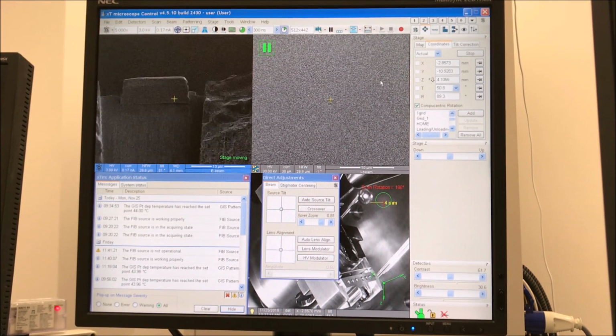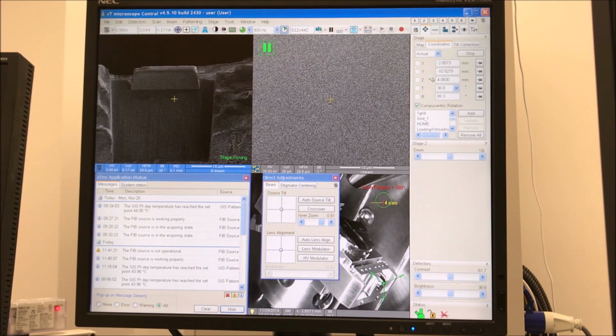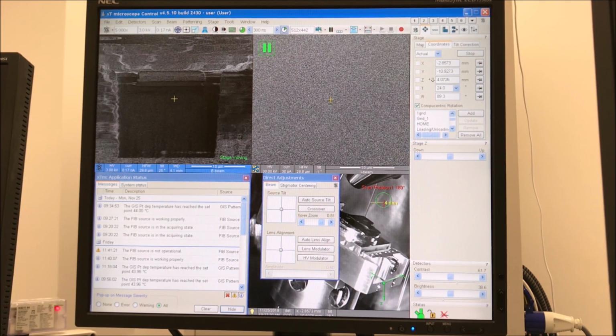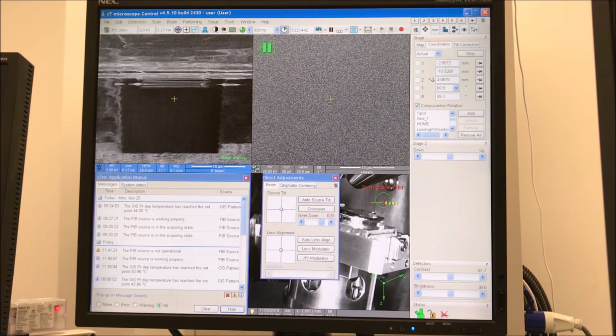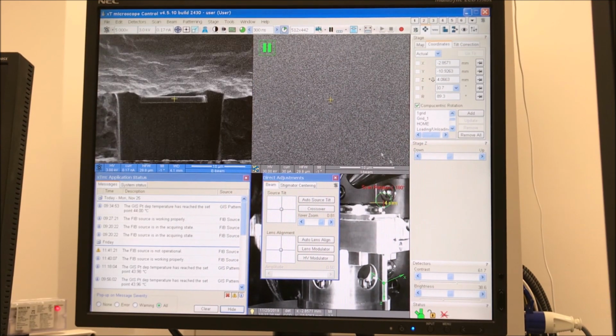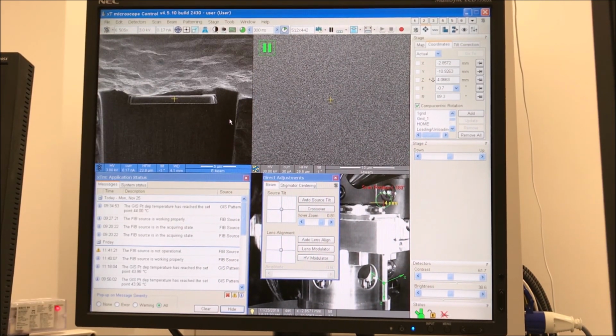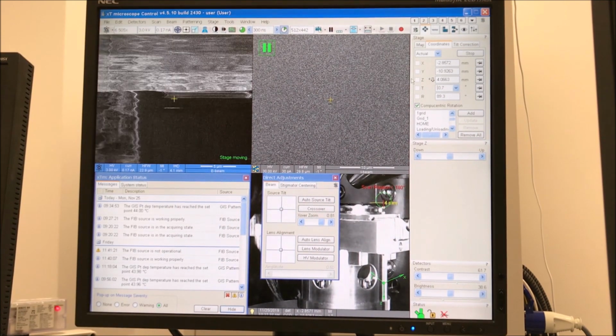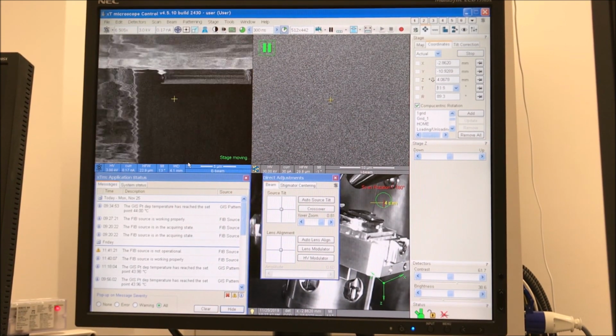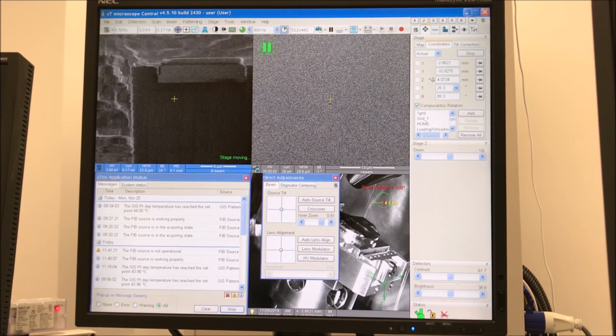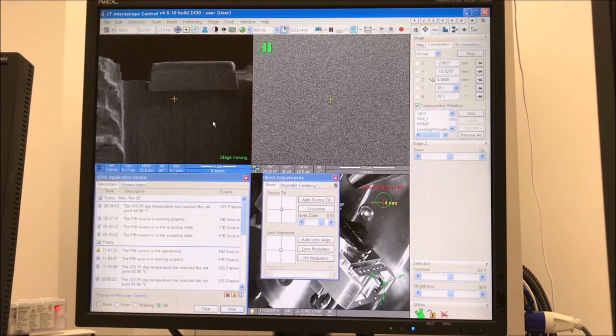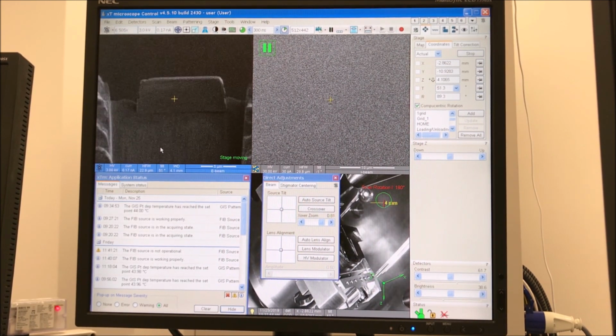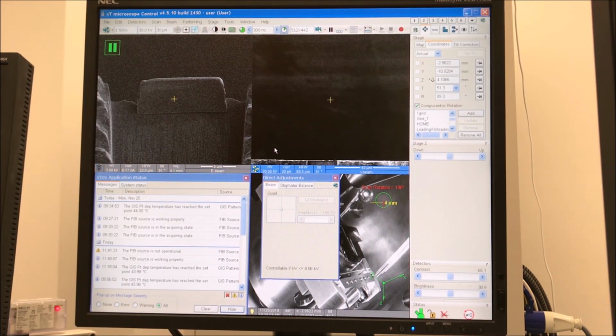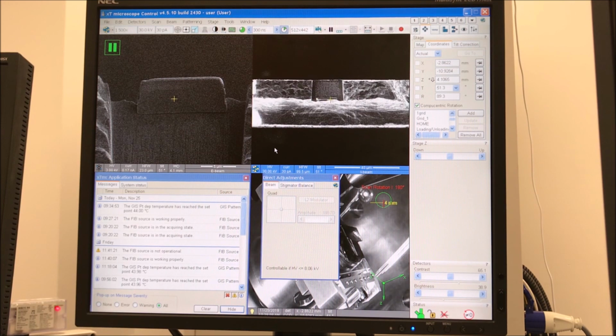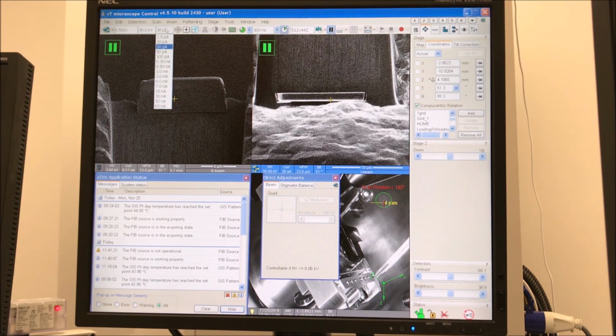the ion beam. So keep in mind, because we tilted minus 0.7 degrees to align the grid, normal incidence now is actually 51.3 degrees to get normal incidence for the ion beam. And so that's important. You want to keep that in mind when you're doing your final thinning steps. Sample is at eccentric height. So I can go to my live ion beam image and I can shift the image so it's coincident with the E-beam.